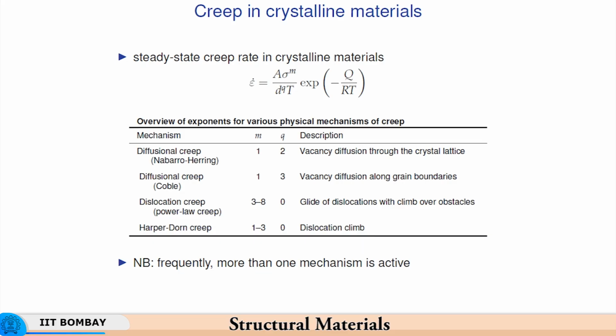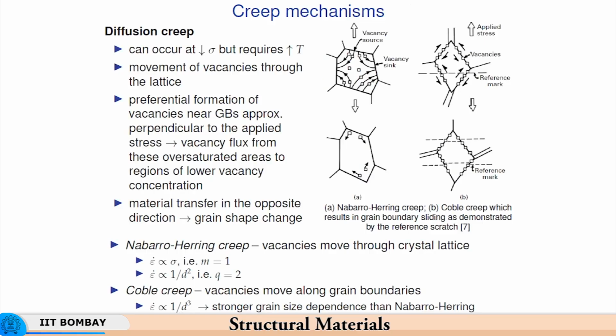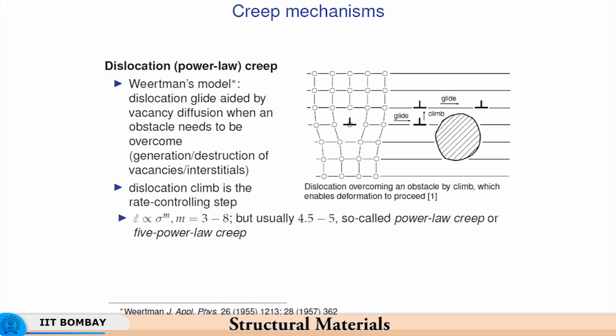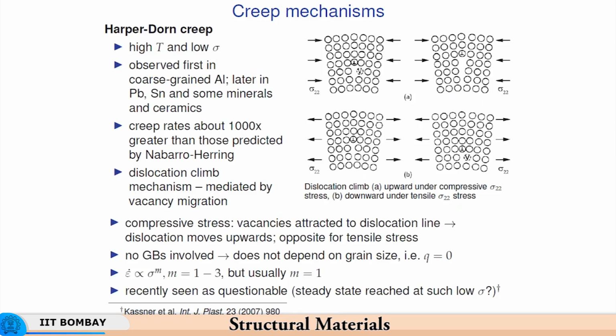and so these are the different mechanisms of creep. And so, if one has to reduce creep, one can see that consistent with the mechanisms we have seen, it is important to reduce the grain boundary area. So, the coarse grain size is the best as far as creep goes, as well as we need to have some metallurgical features or metallurgical factors that will also prevent the dislocation movement if we have to control the power law creep.